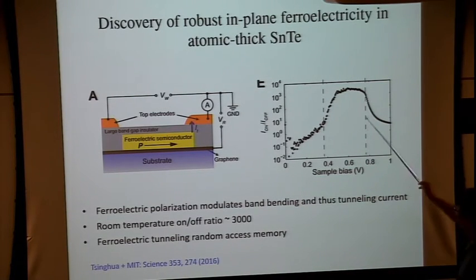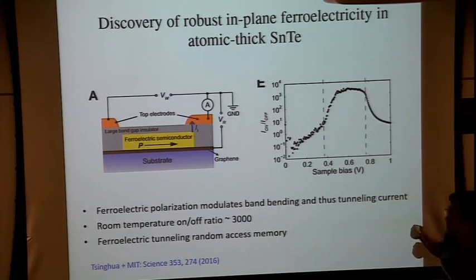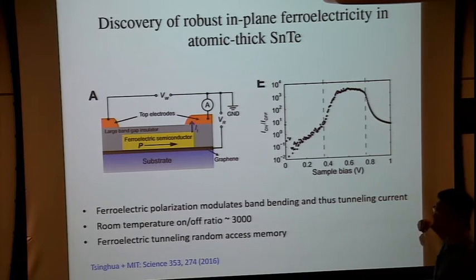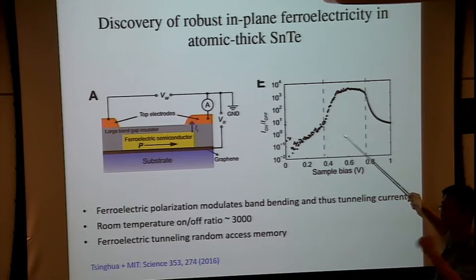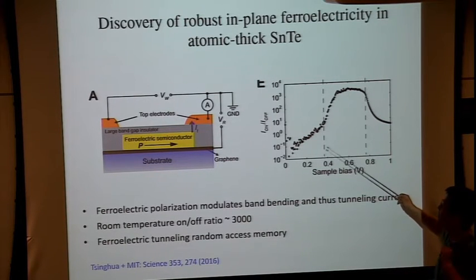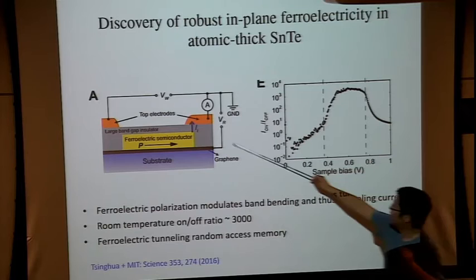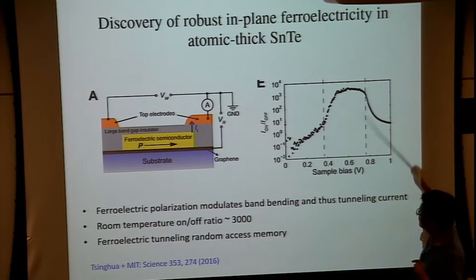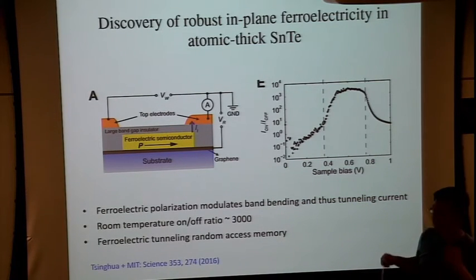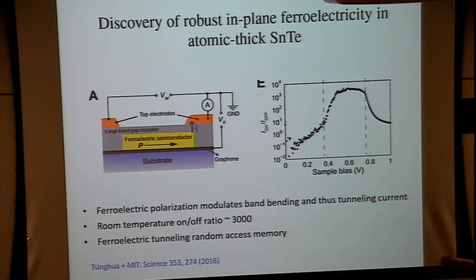And actually, the Tsinghua group followed this proposal. They did this experiment, and you find that as you switch the ferroelectric polarization by a voltage pulse, the tunneling current is different by about 3,000 times. So the on-off ratio is 3,000, and this is done at room temperature. So this perhaps could be used as some sort of ferroelectric tunneling random access memory.